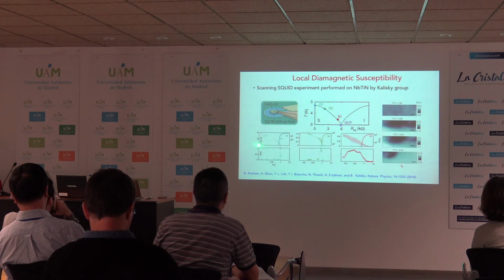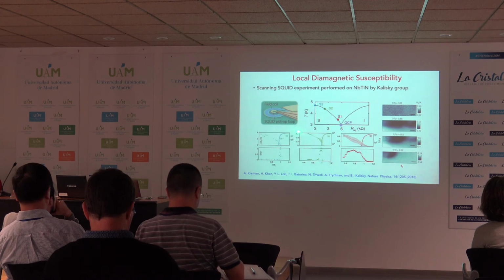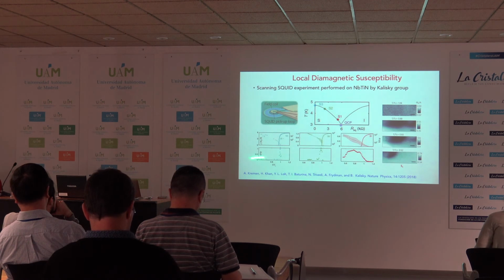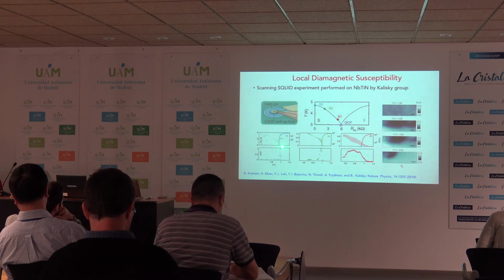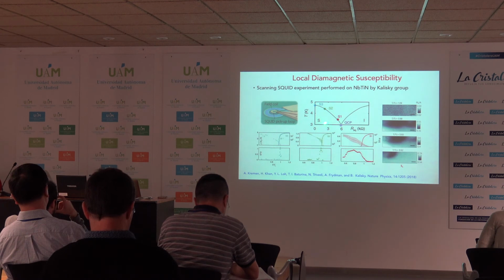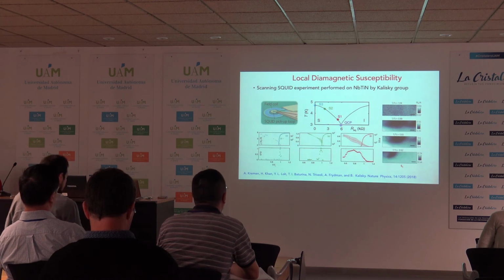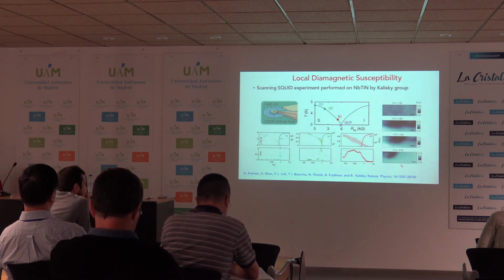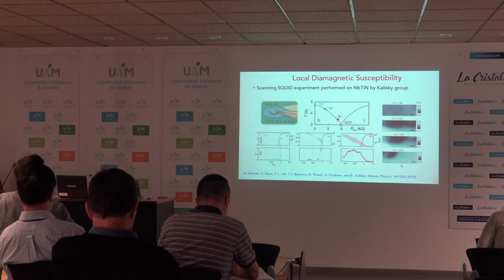When they are far away, what is shown here is the resistance. All three plots are scaled with T over Tc, so that means the thermal fluctuations have been accounted for. This is T over Tc of 1, and what you see is the diamagnetic susceptibility, with the sign reversed, which is large in the superconductor and vanishes at the transition. As you come toward the quantum phase transition, you see that the susceptibility distributions are becoming extremely broad, and that's because of this growing inhomogeneity.